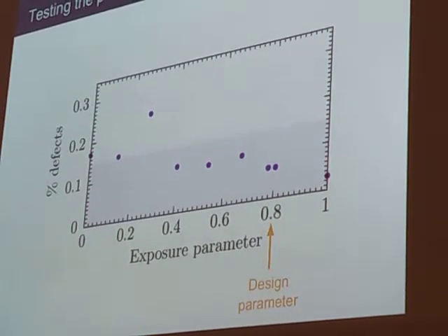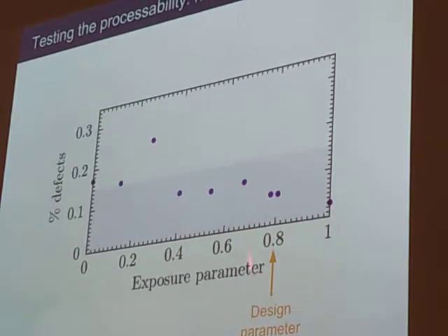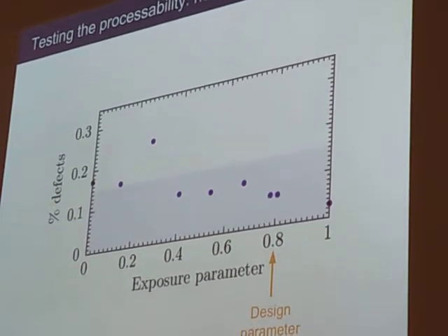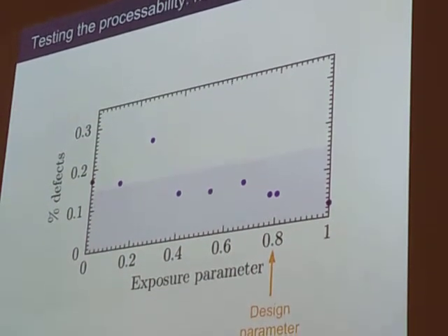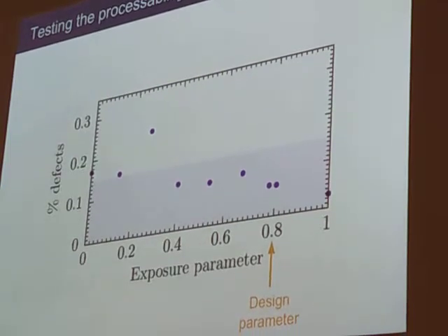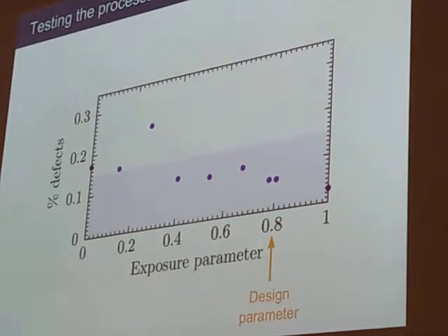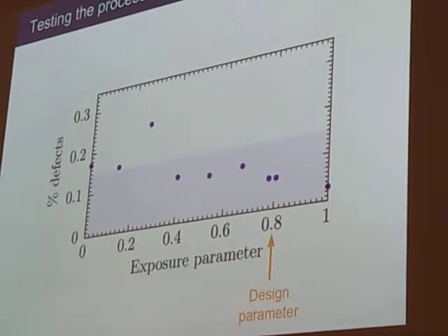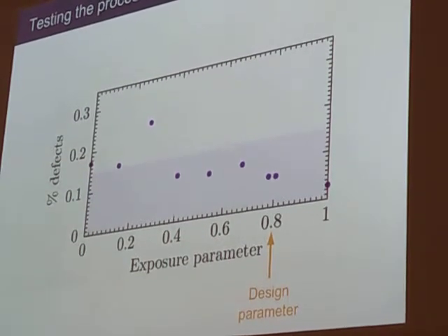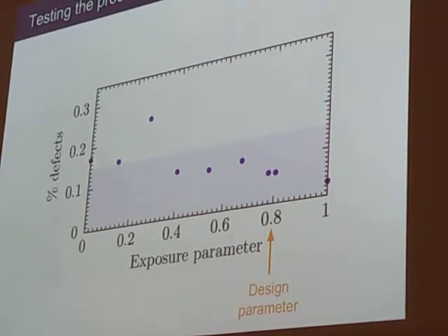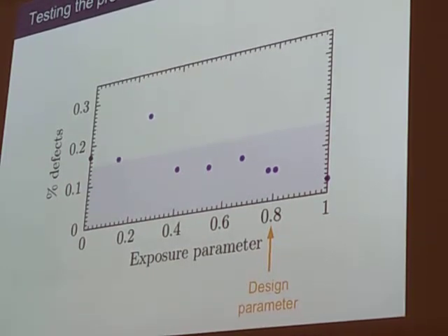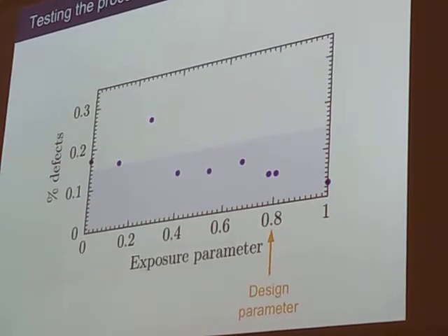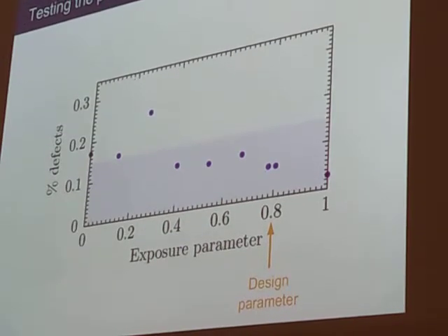Now we proposed this exposure parameter here of 0.8, but because we recognised that it was really difficult to design this alloy, and we're taking big leaps of faith when we're doing that link to weldability and other things, we really needed to test this. So we paid for additional experiments to be performed to plot the amount of defects as a function of this crucial exposure parameter.